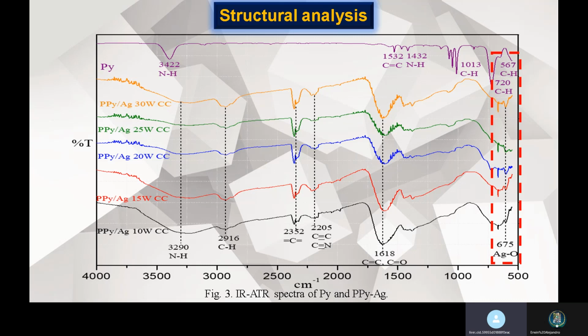In general, the dehydrogenation and oxidation of pyrrole ring and the formation of multiple bands can be observed. It was detected a silver oxygen bond at 675 centimeters to the minus 1, which suggests oxidation of silver. This opens the possibility of chemical interaction between both materials.